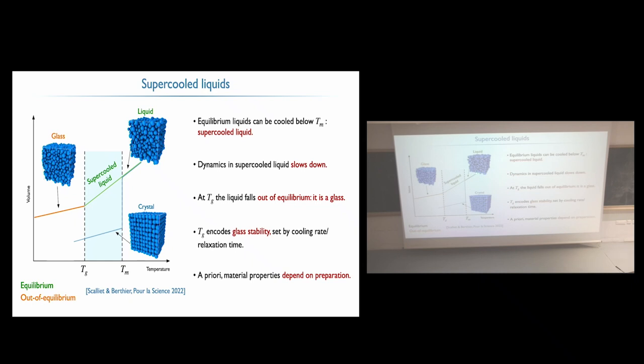And what happens is that you enter a supercooled liquid, so it means that it's cooled below the temperature where it wants to be a crystalline solid. So it's metastable with respect to that, but it's still in equilibrium, still disordered, so basically it just looks like a liquid. But the dynamics here in this blue regime is going to slow down dramatically. This is what you do when you take the glass out of the oven, and at some point it's just so slow that it's frozen. So it's solid, it's a glass, and this is the glass transition temperature here.